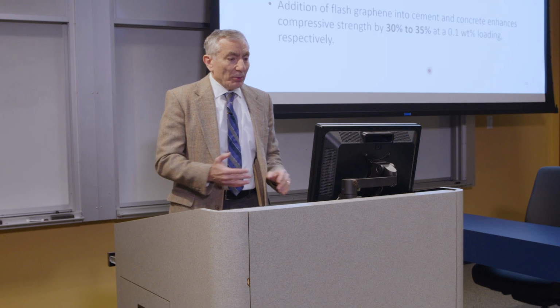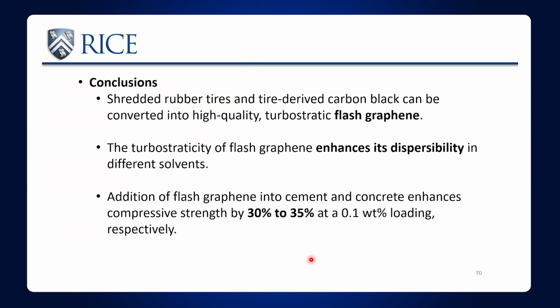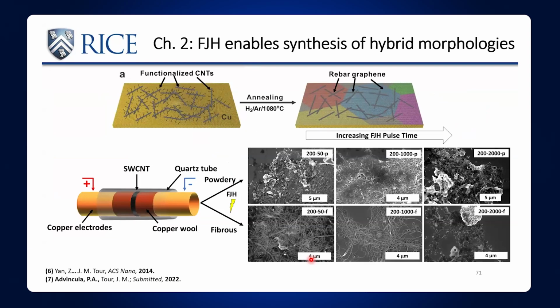All right, so shredded rubber tires can be turned into high quality flash graphene, and then this can be dispersed in solvents better and can enhance concrete. And so one of the other things we did years ago, remember the CVD growth? We said that we could grow graphene just on a copper surface in a CVD chamber. We had put carbon nanotubes on there and grown the graphene, and we got a melding of the nanotubes to the graphene. Well, we did something similar where we put carbon nanotubes in here as our source. And then when we flash it, you can see where the carbon nanotubes, but you can see where some of the carbon nanotubes have turned into graphene.